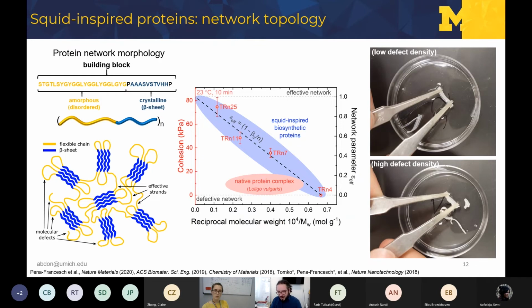So this is a long-standing challenge in polymer networks, and it's very difficult to have a controlled network topology, right? So what we could do, by controlling not only the molecular weight but also the sequence and the size of the nanocrystals, is build a model that could predict this molecular defect density, and we could optimize the structures beyond what we find in nature. And you can see here, this red bubble is what we see in nature, but by playing with the molecular weight, we can improve the topology beyond what we see in nature and reduce the molecular defect density.